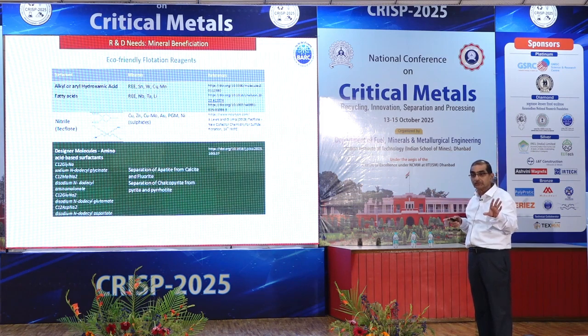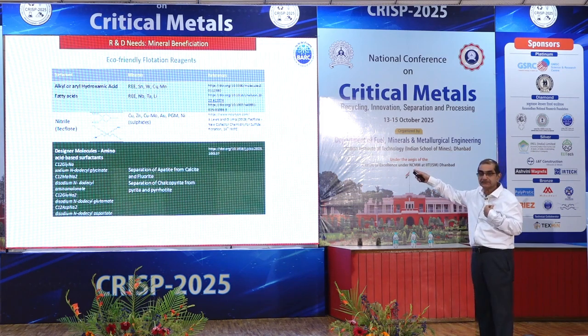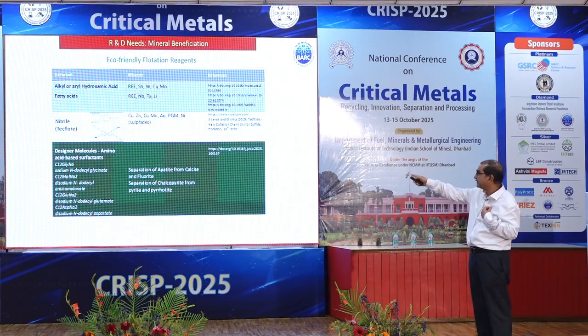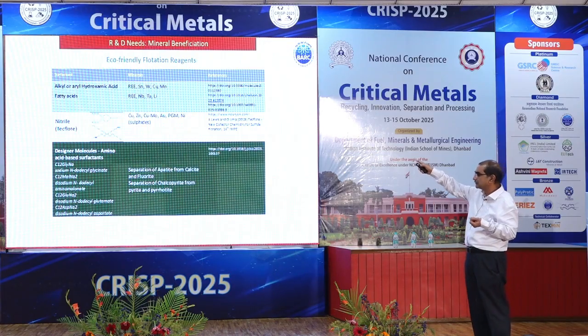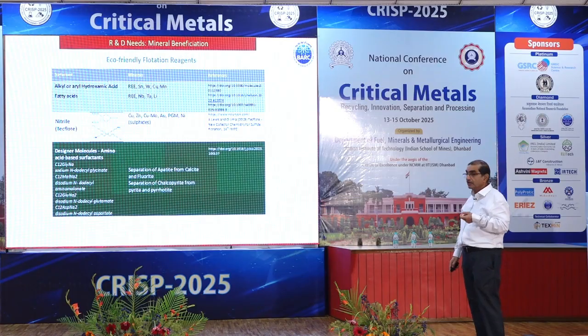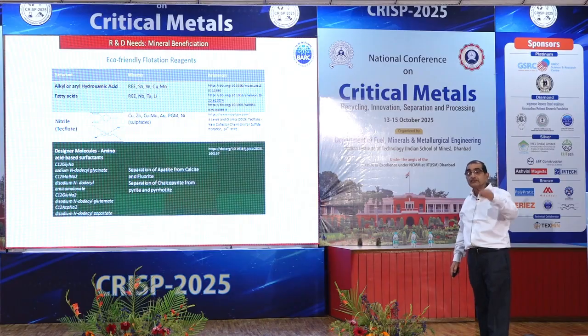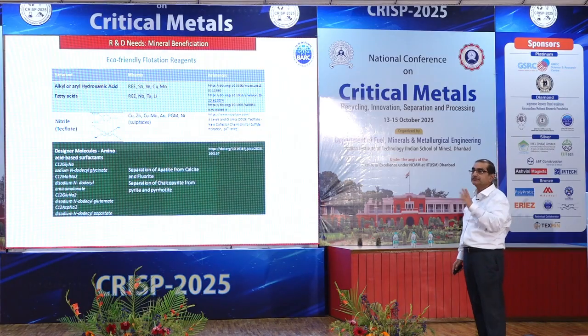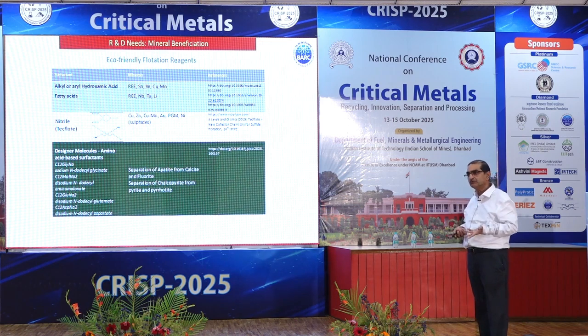Xanthates will spoil the environment. That should be replaced by nitrile based reagent. Similarly, bioderived surfactants should be synthesized and used. Let me give one more extension on hydroxamic acid. China is achieving success in critical minerals because they developed more than 20 or 25 variants of hydroxamic acid functional groups, and they are quite successful in utilizing those. So we need to do certain work on this, and we have to replace the conventional reagents with these.